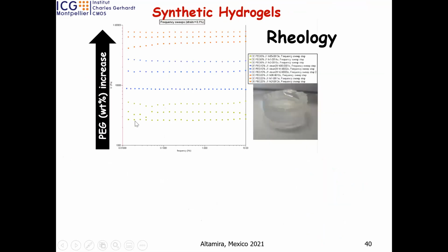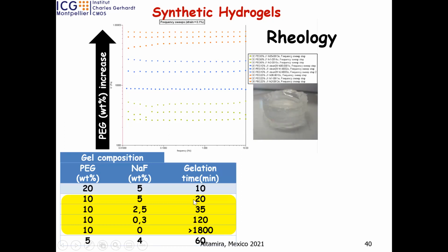The mechanical properties can be controlled. If you increase the amount of polymer, you increase the mechanical property, and of course if you decrease it, the viscosity decreases. Here I would like to show you how we select our conditions. You have the percentage of PEG, sodium fluoride, and gelation time. Why is it important to control the gelation time? It's just for